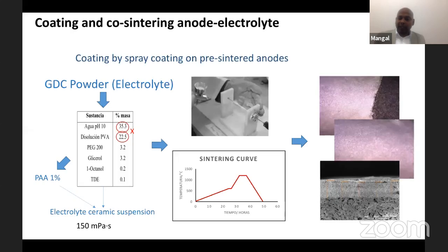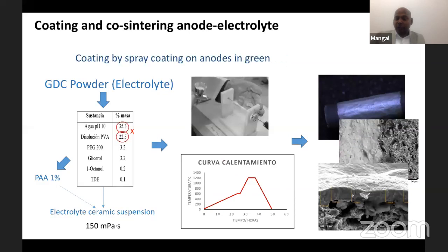So this is how you can innovate new spray coating also. We have filed a national patent, but that is still under processing. With this coating we have achieved nearly 100% density, meaning minimum porosity, in the homemade spray coating. On the right hand side, you can see the anode tip in black color, and over that, in white color, the coating. You can see the microstructure, how dense it is, with the grains arranged over the porous microstructure of the anode.